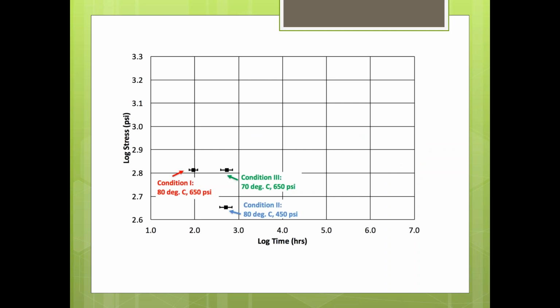So I mentioned 3 runs or 3 test conditions before. In the F3181 testing, basically those 5 samples are really 15 samples, but 5 per condition are tested at elevated temperatures and elevated stresses to accelerate the failure mode and to give us the ability to extrapolate that to a stress time curve, if you will, a log curve, to determine how long it's going to last given that stress level and condition. So the tests are done at 80 degrees Celsius, 70 degrees Celsius, 650 psi, and 450 psi in combinations to give you the 3 test conditions.